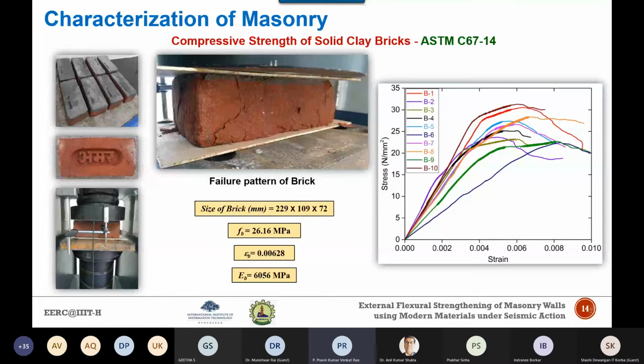So the compressive strength of the brick has been determined using ASTM standard guidelines, using direct compression. And here you can see the nominal size of the brick, a non-modular brick, is 9 inches by 4 inches by 3 inches, and the brick strength comes out to be almost 26 MPa. So we have tested almost 10 bricks, and the average strength we got is 26 MPa, and the modulus of elasticity is in the range of 6000 MPa.